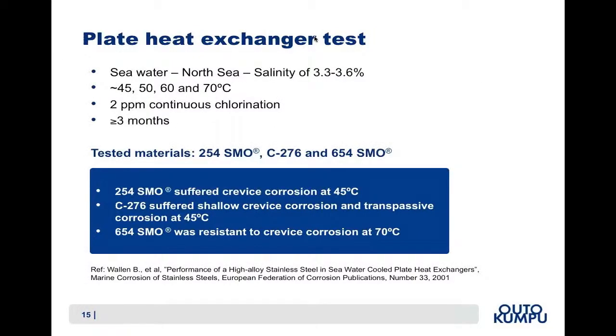Now, in an example of 654 SMO used in a plate heat exchanger, this was a test carried out in seawater with a salinity of 3.3 to 3.6%, tested across a range of temperatures and for a period of more than 3 months. The outcome was quite clear. While 254 SMO suffered crevice corrosion at 45 degrees and C276 suffered shallow crevice corrosion at 45 degrees C, 654 SMO was resistant to crevice corrosion at 70 degrees C.